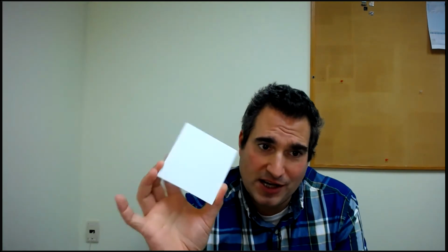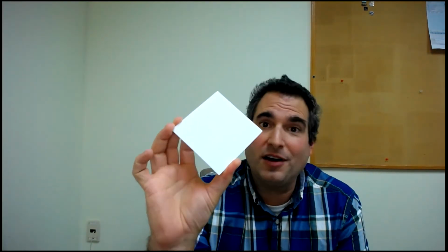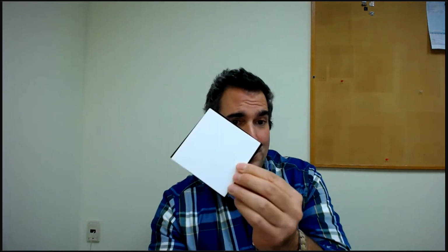So what we then do is we take our ceramic. In this case, this could be aluminum oxide or beryllium oxide based on the brilliant white color that you see here. Okay, so we've taken our raw copper cut to size. We've chemically oxidized it. We have our ceramic. We put them together like so, as well as another piece on the bottom. And we run them through one of our belt furnaces at over 1,065 degrees C.